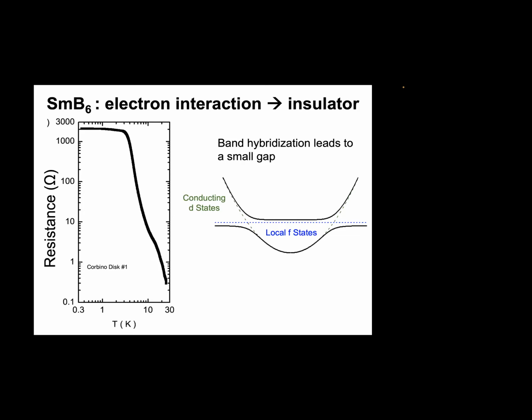And indeed, this is a correlation effect in the sense that we have the hybridization between the local f states and the conducting d states, and hybridizing gives a teeny tiny gap. This gap is only on the order of a few or less than 10 meV. But magically, the chemical potential at low temperature sits inside the gap. As a result, it turns into a narrow gap semiconductor, and that's where this activation behavior came from.